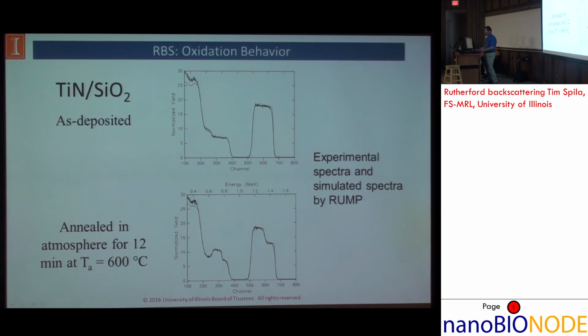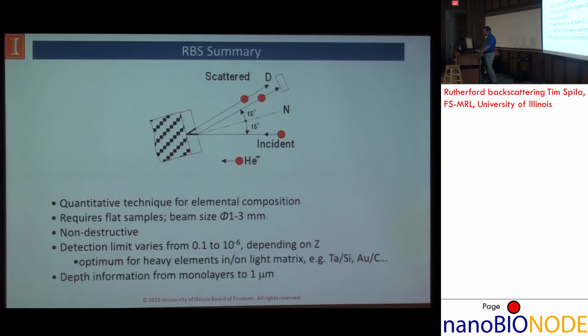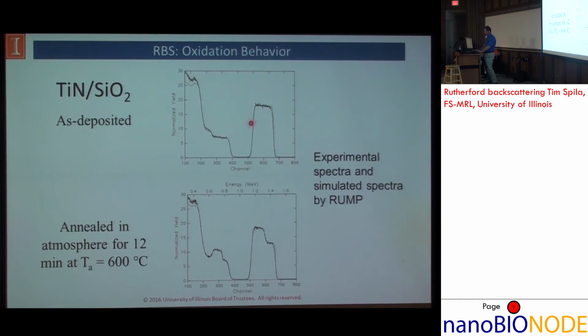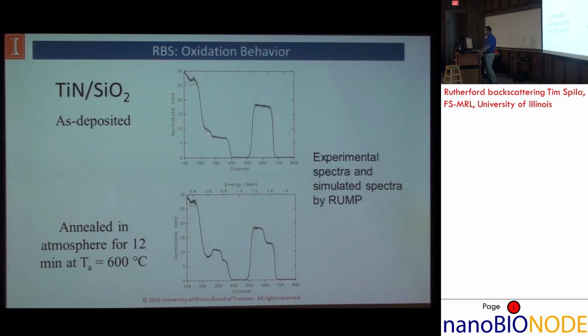And this was an example of oxidation experiment done with titanium nitride on SiO2. So this is your sample with the titanium peak here, and you have some nitrogen peak here. And then when you oxidize, you actually drop the level of the titanium peak by one sixth. That's because you're going from TiN, where it's 50%, to TiO2, where it's 33%. And then you also pick up an oxygen peak here. From this, of course, we can then get the thickness of how far into the titanium nitride you've actually oxidized.